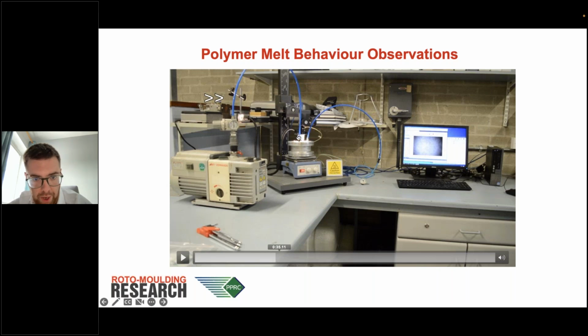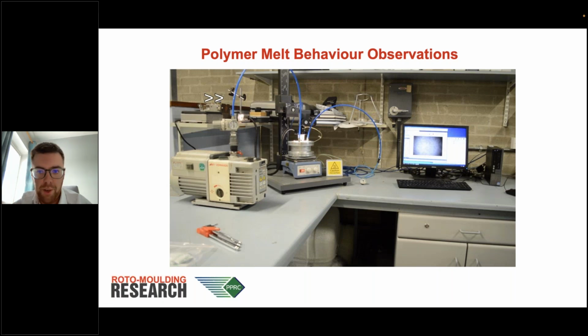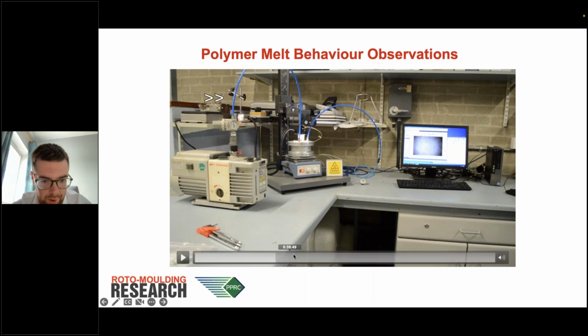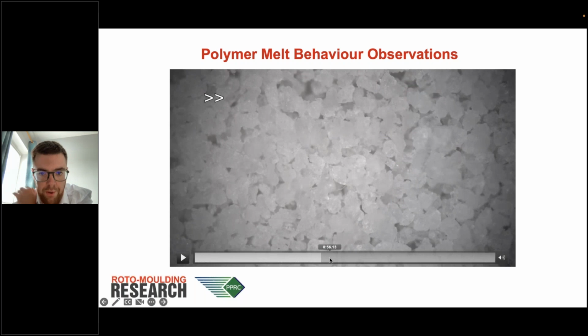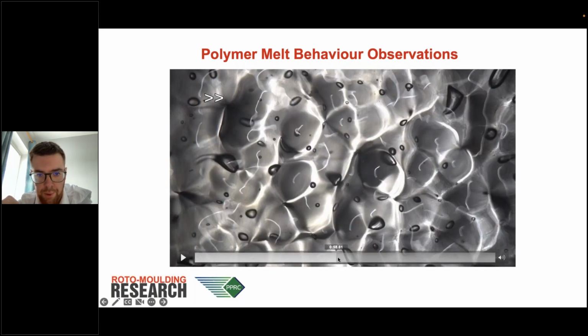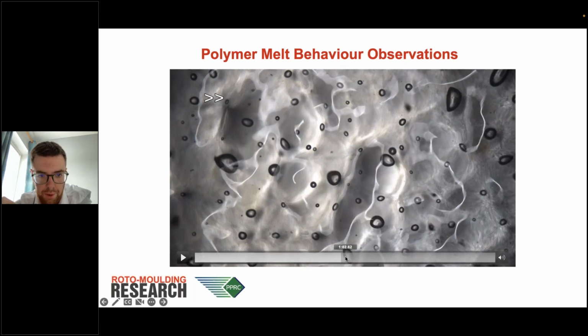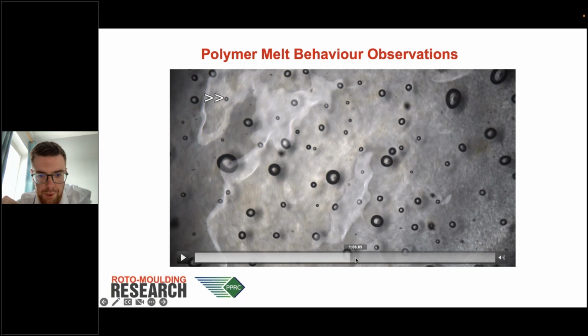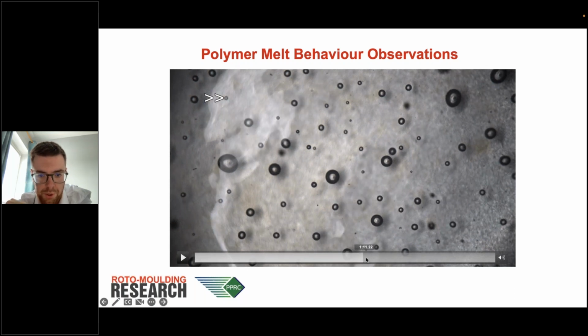And what we have is a camera with a light that is shining down through the glass, looking onto the polymer melt. You can see that on the PC to the right-hand side here. And what I have over this side is a vacuum pump, so I'm able to experiment with the pressure and its effects on the polymer melt instead of controlling the densification behavior using particle size. So I'm going to explain that a little bit more in the pictures that are captured during the experiment. So the first set of pictures here is for an experiment on a standard rotational molding powder not done under any pressure. And you can see that polymer melt forms and these bubbles remain fairly constant in size through the duration of the experiment.